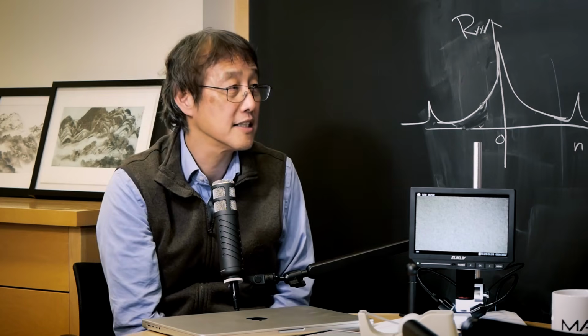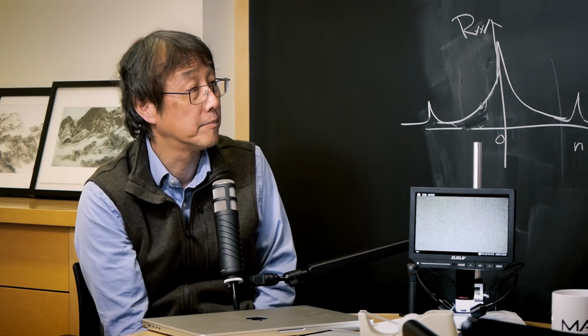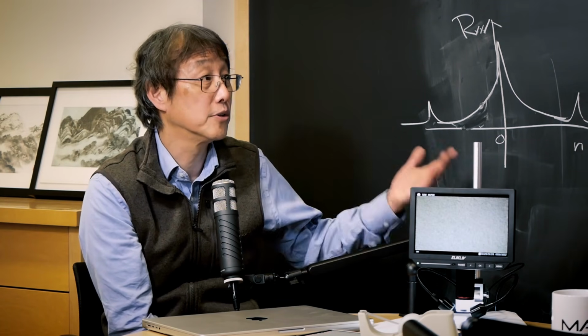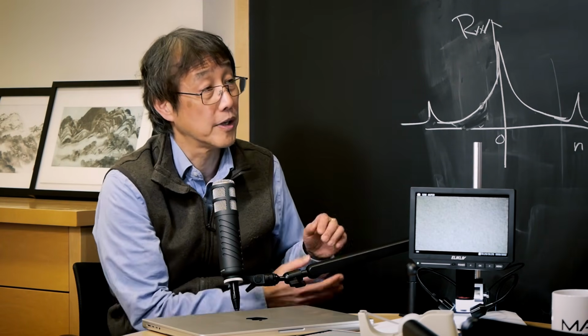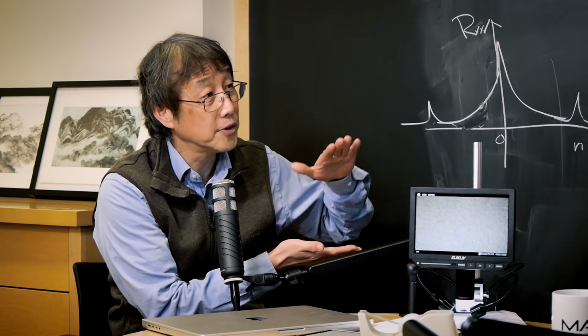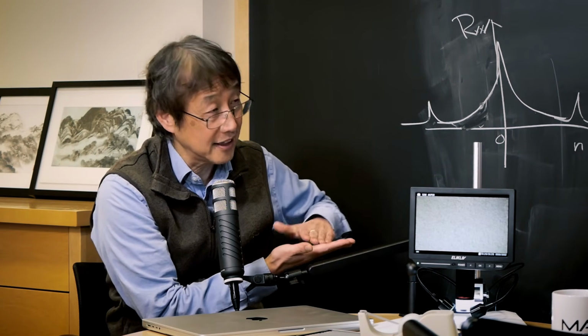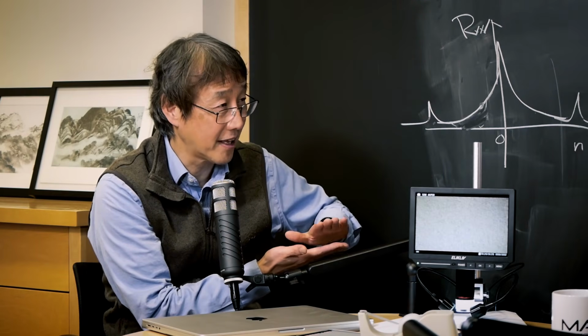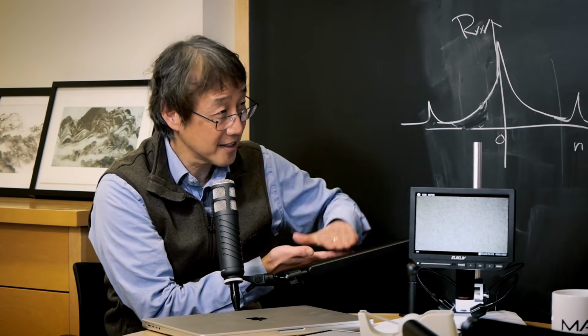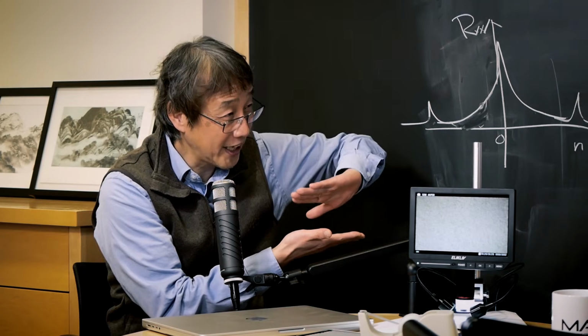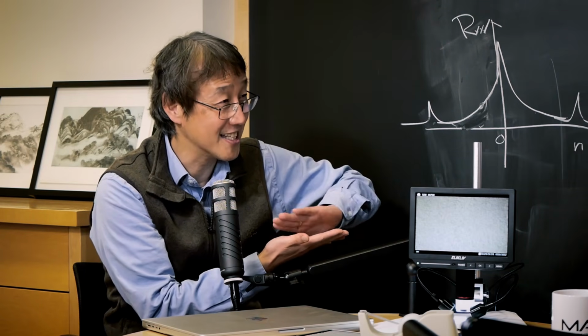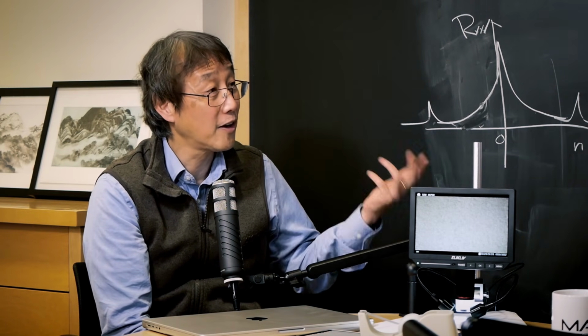I think this method was initially proposed by yet another group, at UT Austin, Emanuel Tutuc's group, who first demonstrated the cut, tear, and rotate method. Basically, you tear the crystal starting from a single crystal, you rotate it and put it back. Mechanical stability is what determines that twisting angle, right? That method was developed but was perfected by Pablo's group. So it aligns on the edges, basically. It just depends on how you cut it.